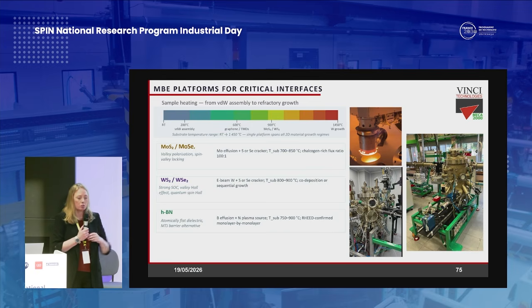So for example, with regards to the MBE platforms, we do a lot of work on, let's say, high temperature substrate holders, so being able to go to 1200 or 1450 degrees, which mechanically speaking is not a simple solution. But it's something that we achieve by learning a lot from how long our customers are going to stay at those critical temperatures.